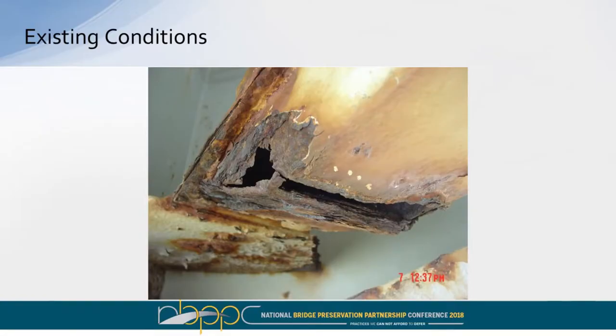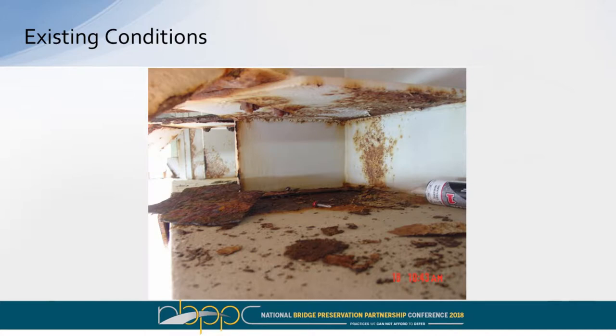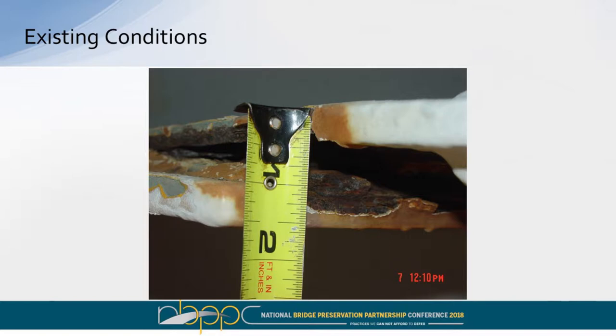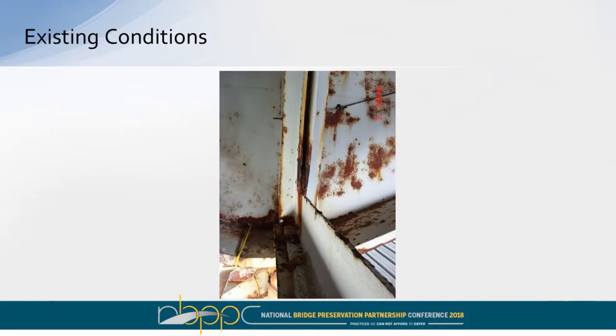Now tying into existing conditions prior to the 2010 steel coating operations. On these 8x8 square tubings that frame up the unit, we saw a lot of localized corrosion — basically just a cavity that grows. Then we have accumulation of water where the internal stiffeners and bottom flange tend to collect water, and you just start seeing acceleration of corrosion. We sounded some areas and found holes — it's not as thick as it once was. Your nominal thickness gets thinner and thinner. We also have pack rust that breaks welds or just pushes things where they don't belong.